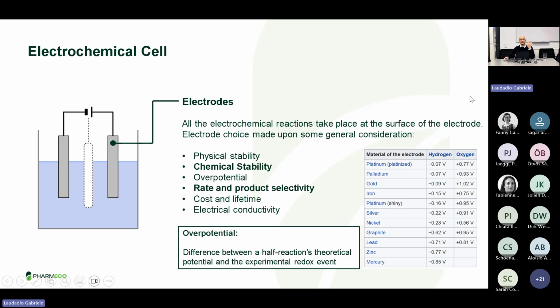And most of the time it's a parameter that dictates which kind of event is more, let's say, favored in the electron transfer process. So, for example, here we can see that platinum has a very low overpotential for hydrogen. So, in principle, the reduction of hydrogen is very favored for platinum, while that's not actually the case for mercury, where the discrepancy is higher.